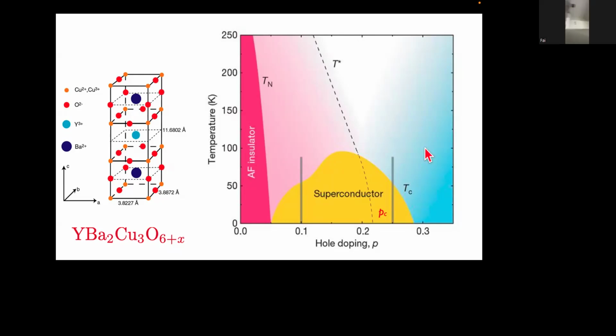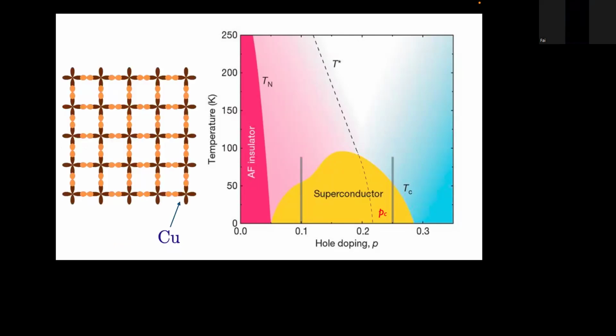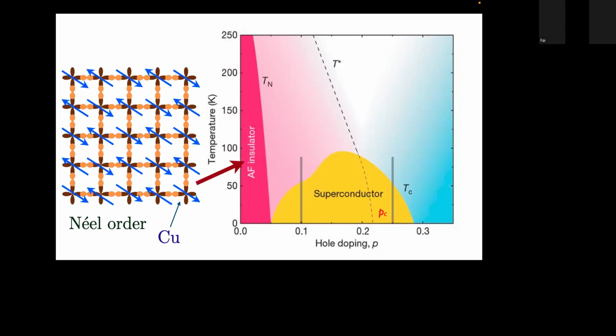So let's look at the different phases here above Tc. Oh, before I get to that, sorry. At zero doping, which is the simplest limit and is now well understood, it's an excellent approximation to think of this material as just a bunch of copper atoms on a square lattice. Even simpler, you can imagine there's just one electron and one orbital on each copper atom that's active. Now, the electron has a spin, and so what happens in this region called the AF insulator is that the spins polarize in this antiferromagnetic configuration, sometimes called Néel order, where it's like a chessboard, where the black squares are down and the white squares are up.